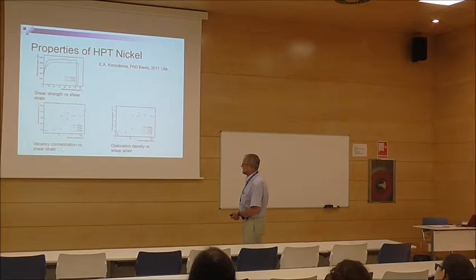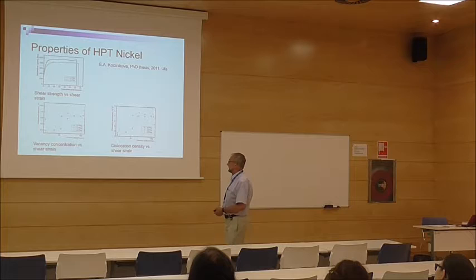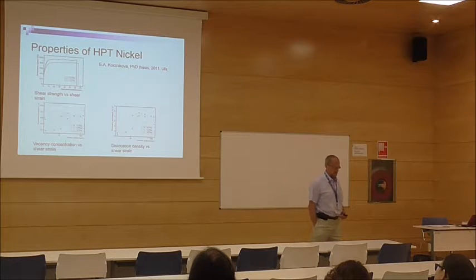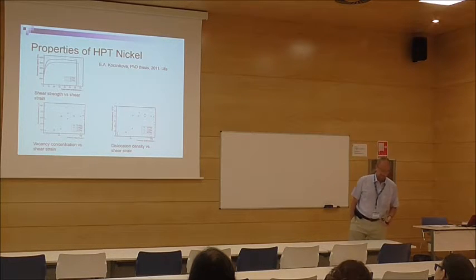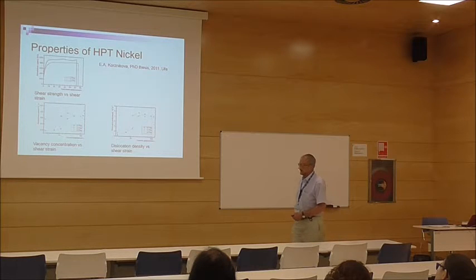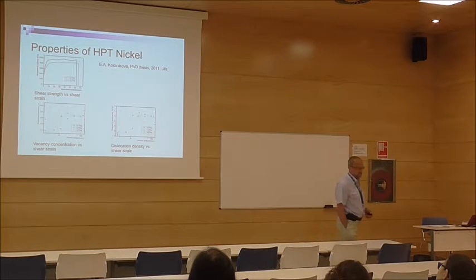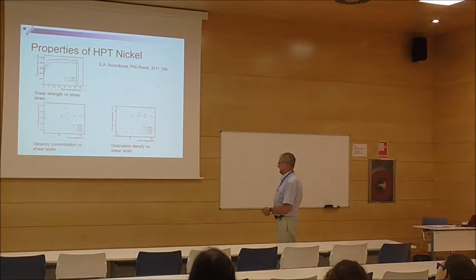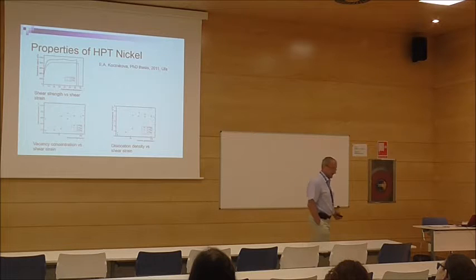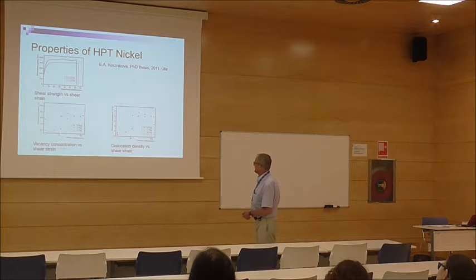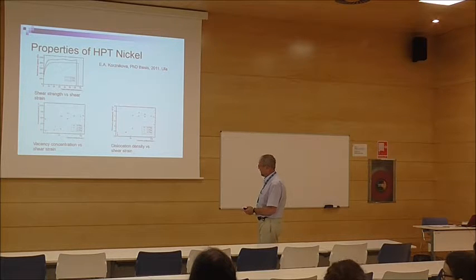Then, if you measure vacancy concentration versus shear strain, you can get up to 10 to the minus 5, a huge amount of vacancies, and Professor Zhilyaev claims that all of these vacancies are actually responsible for the unusual properties of HPT materials. Also the dislocation density is very high, closer to 8 times 10 to the plus 15 per square meter.